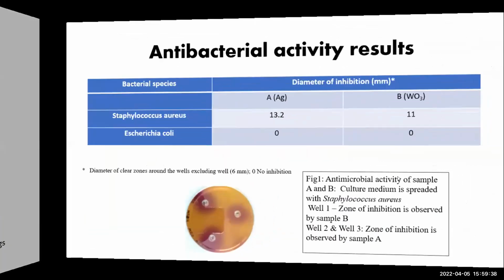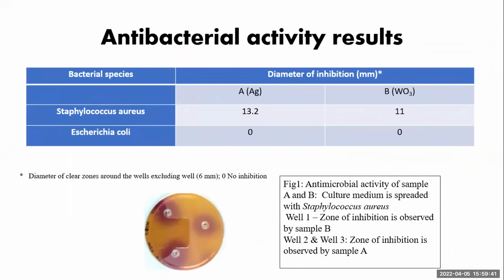And after that we discuss the antibacterial activity result. The antibacterial activity of Ag and WO3 was tested against two bacteria. First is S. aureus and second is E. coli. We found inhibition of S. aureus bacteria with a 13.2 mm diameter for Ag and 11 mm for WO3 nanoparticles, and for E. coli bacteria 0 mm diameter for both nanoparticles.